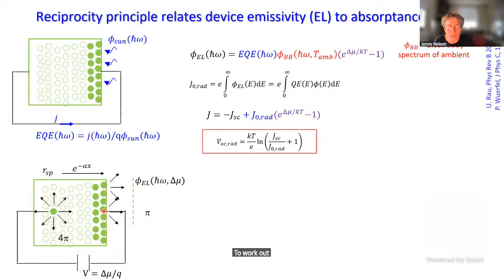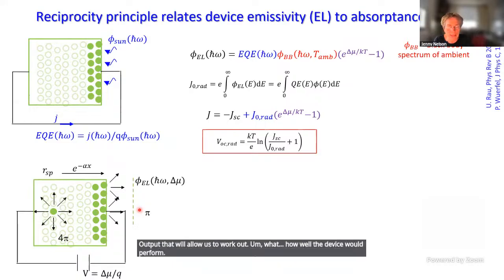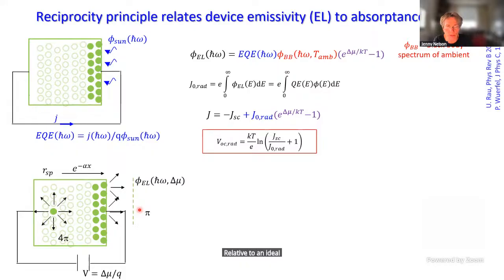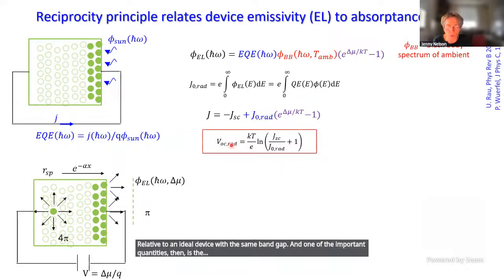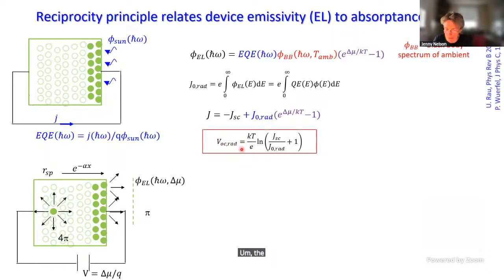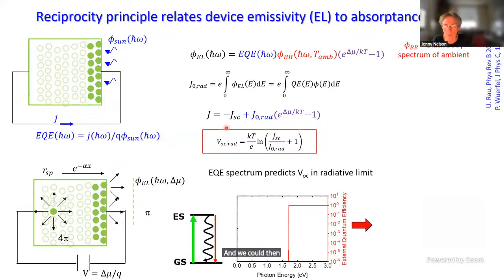If we measure the amount of light that our solar cell gives out when we run it as an LED, that gives us the electroluminescence output, which will allow us to work out how well the device would perform relative to an ideal device with the same band gap. One of the important quantities is the voltage that the device would have in the radiative limit. We call that the VOC rad, and we can then compare that with the real voltage.